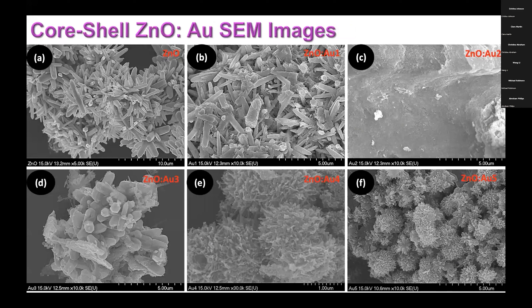These are the SEM images of the core-shell ZnO-Au. In the first image we have pure zinc oxide nanoflowers. As the Au concentration increases with HAuCl4 from 0 to 30 millimolar, we obtain different microstructures moving towards a nanosponge structure. This also confirms that as we proceed to the final sample, the encapsulation of gold increases from the first sample to the last sample, and finally nanosponges are obtained.